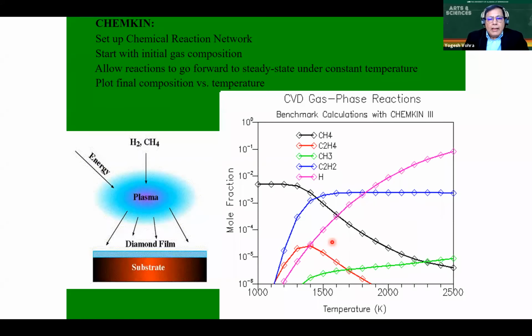So here the plasma chemistry issue becomes very important. So let's just imagine we have a microwave source. We have input gas of hydrogen and methane. We dump some energy into it. We have this plasma, and I showed you a schematic how the diamond film grows on the substrate. But now if you look into the chemical kinetics, the so-called ChemKin calculation of what are the species which are present in the plasma as you increase the gas phase temperature.